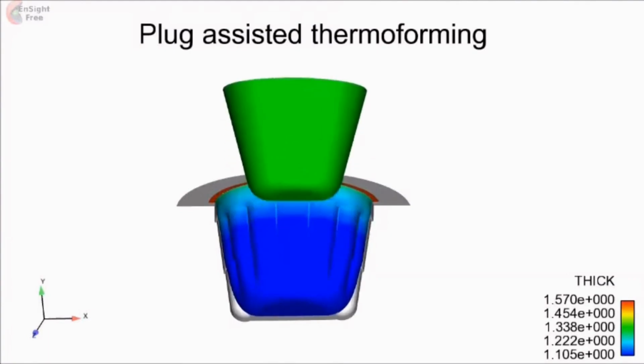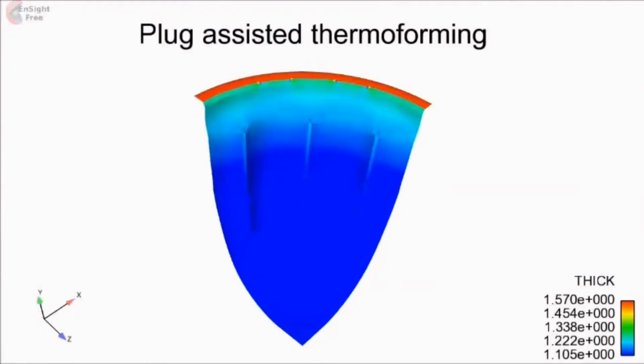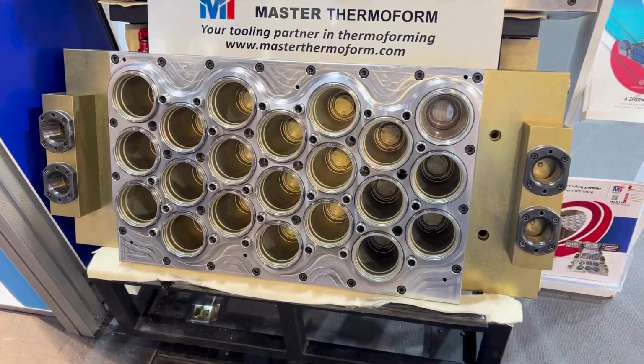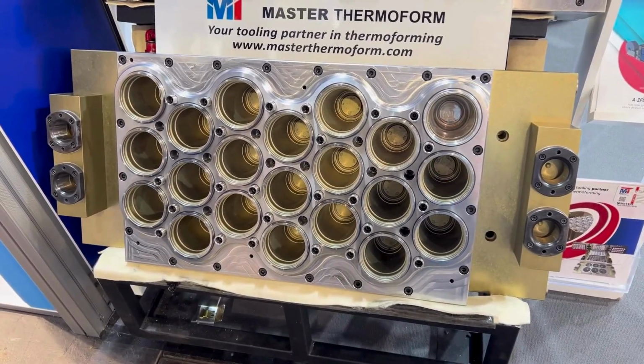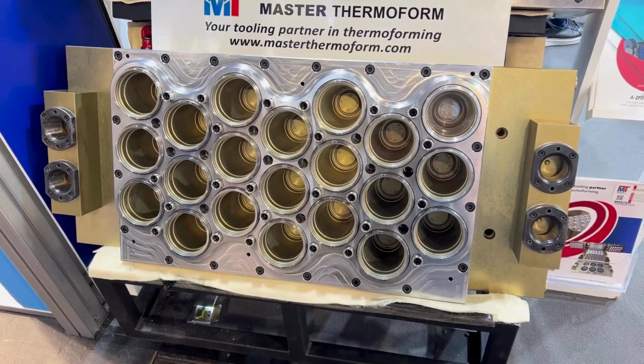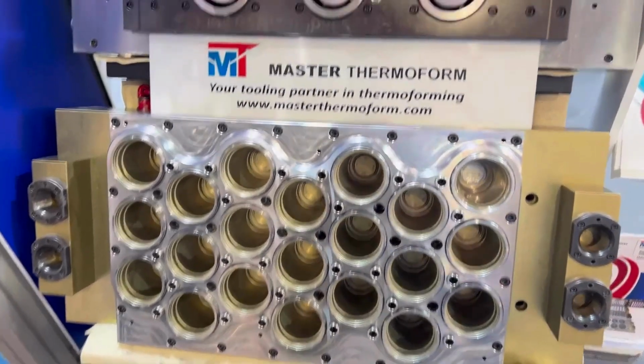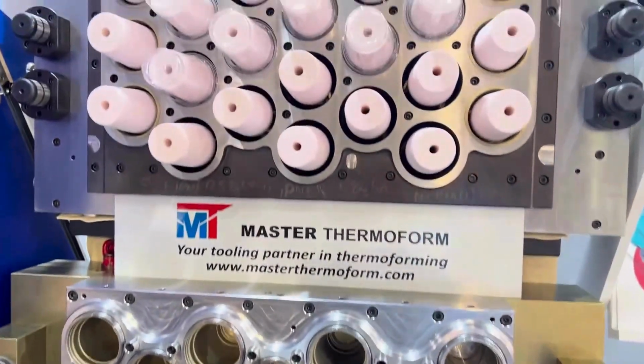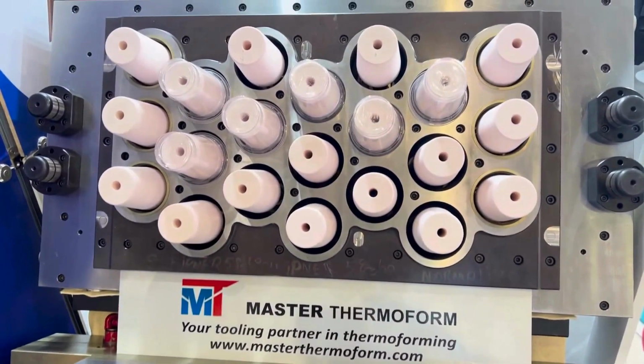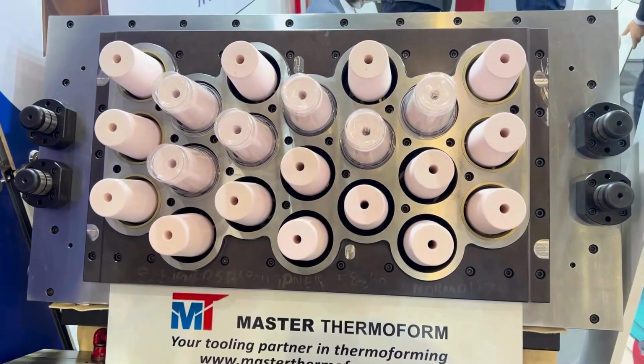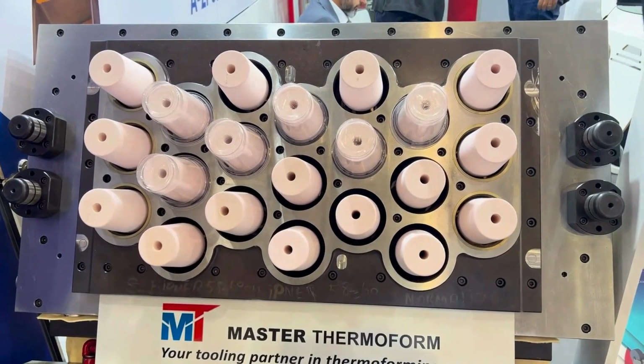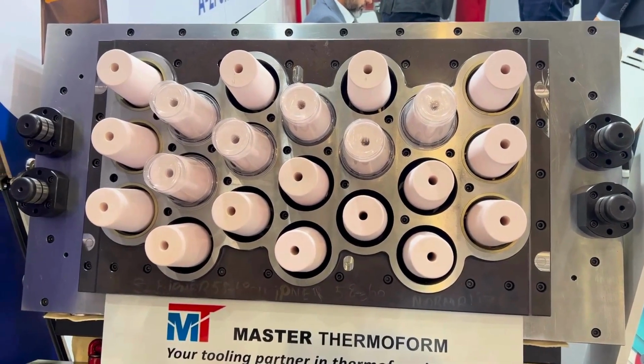The primary engineering value of a plug assist is improved material distribution. In deep draw or high aspect ratio geometries, an unsupported sheet can overstretch, leading to thin spots and localized mechanical weakness. By engaging the plug first, we pre-stretch the material in a more uniform way. This results in tighter thickness tolerances, more predictable strain profiles, and a stronger final part.